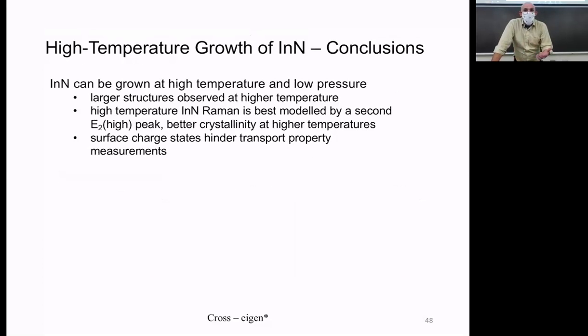We've observed that it can be grown at high temperatures, way above the decomposition temperature, at least what we thought was the decomposition temperature. The reason it can be done is because of the plasma. Every time that indium nitride was documented growing at 650 degrees, it was always done in the presence of other things, like methyl groups, like hydrogen. And what we did was we completely removed that from the equation. We changed it from working with nitrogen that needed to be charged to pre-charged nitrogen. We ionized the nitrogen before we even introduced it into the system, so it didn't need to have anything else done to it. And it made it significantly more reactive.